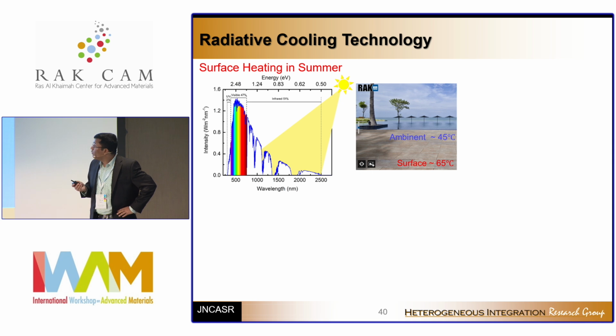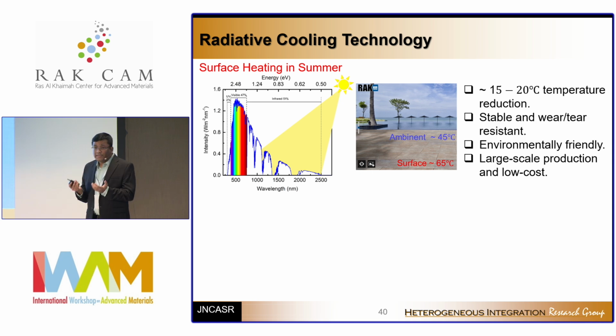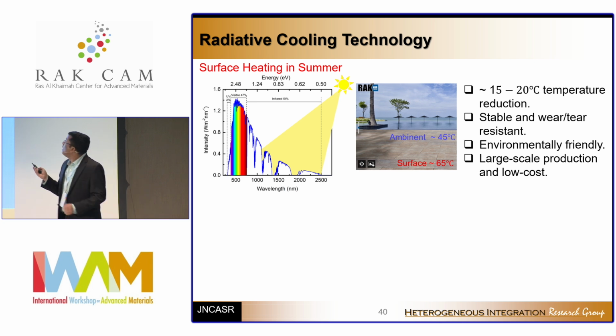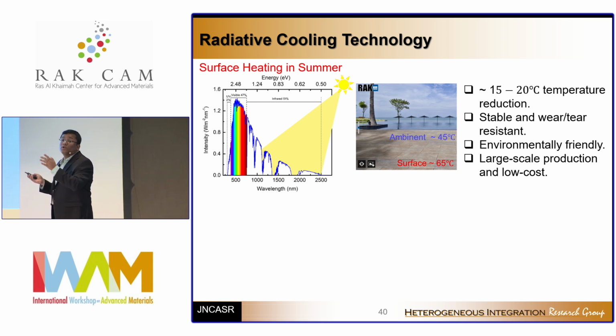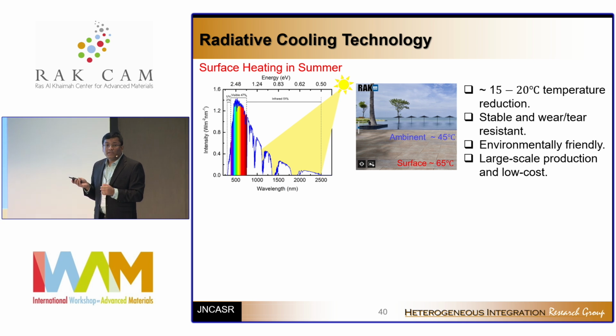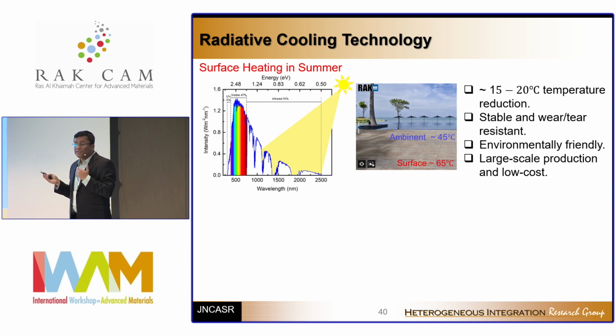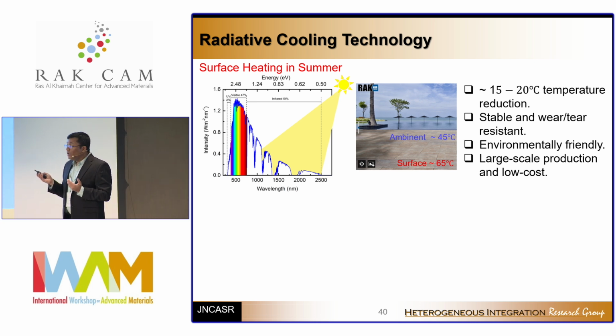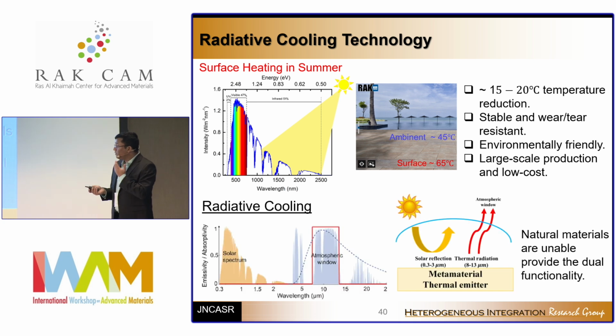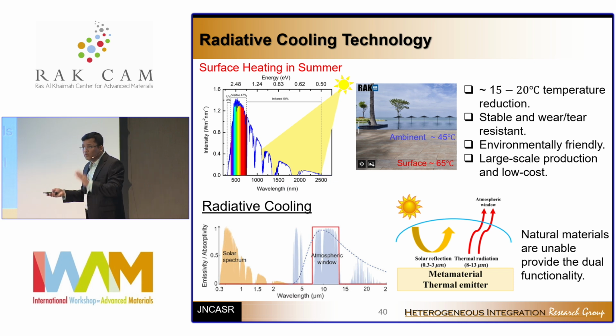So we were asked to design a radiative cooling solution which will cool these surfaces 15 to 20 degrees below the ambient temperature. But more importantly, it has to be stable, reliable, environmentally friendly, and it has to have very low cost and be very easily solution processable. The scientific principle is very simple, as I explained. If sunlight is giving you the heating, you make sure that you reflect the entire solar spectrum. You don't allow anything to heat up your sample.